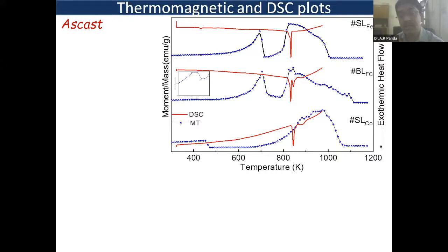So in your DSC plot, the red line peak is somewhere in the rising second stage. So what happens? The amorphous materials are non-crystalline, so when they try to crystallize, that is evidenced by the DSC plots. They crystallize in the form of iron silicide, cobalt silicide, and so on. Right, and this is the initial Curie temperature of the cobalt. Cobalt shows a much lower Curie temperature, and this is the higher Curie temperature in the case of iron, which is evident from the bilayer.